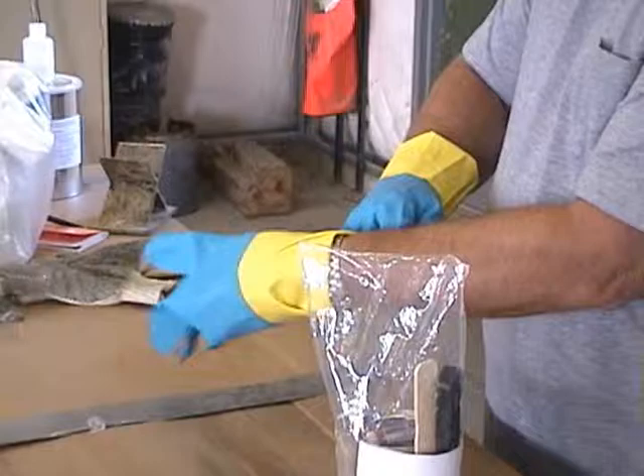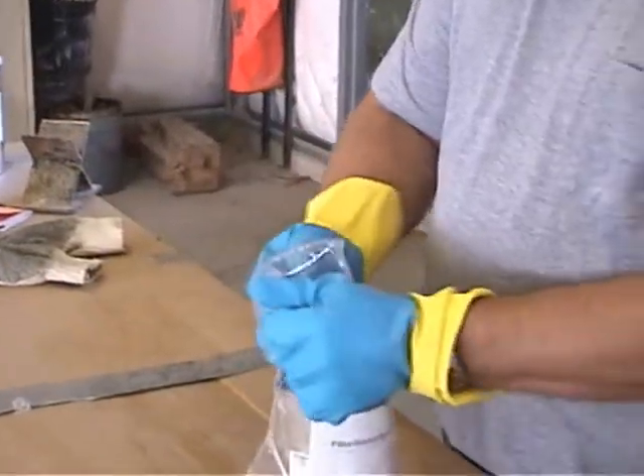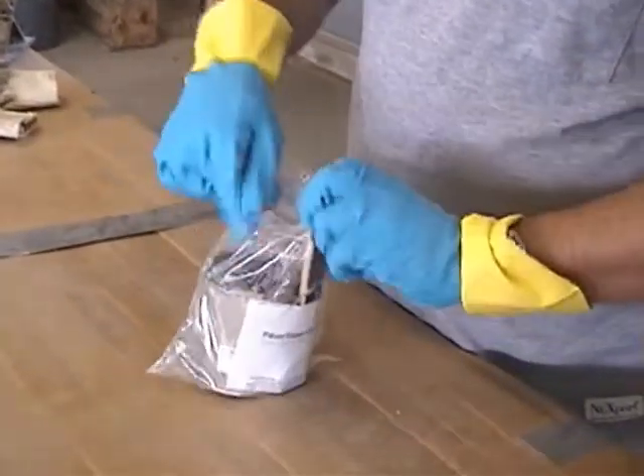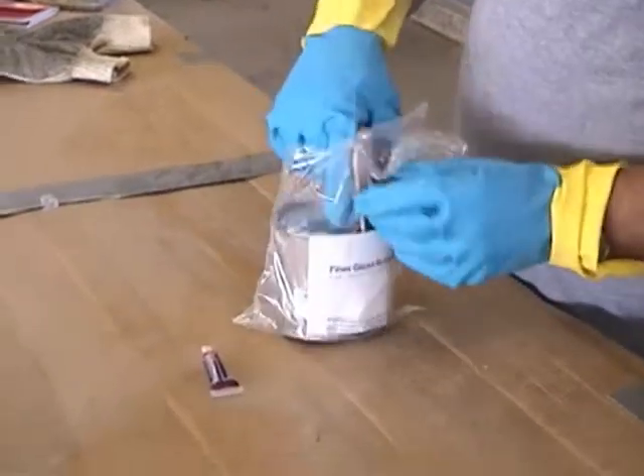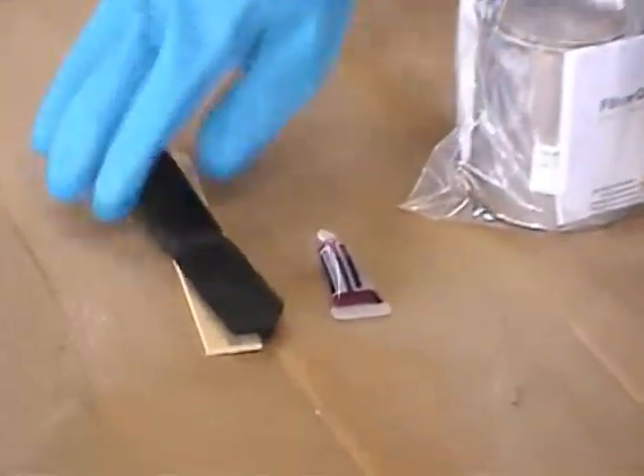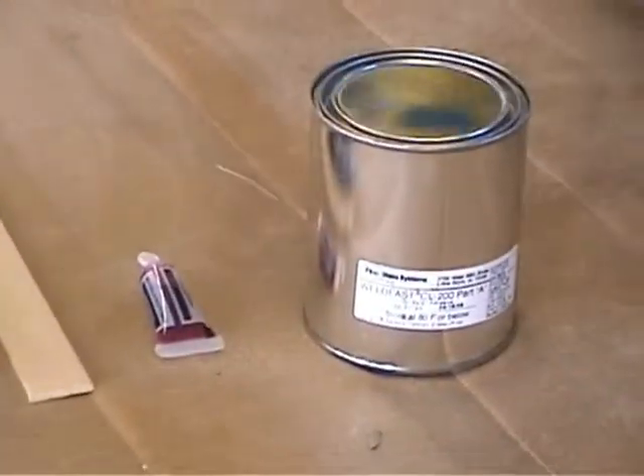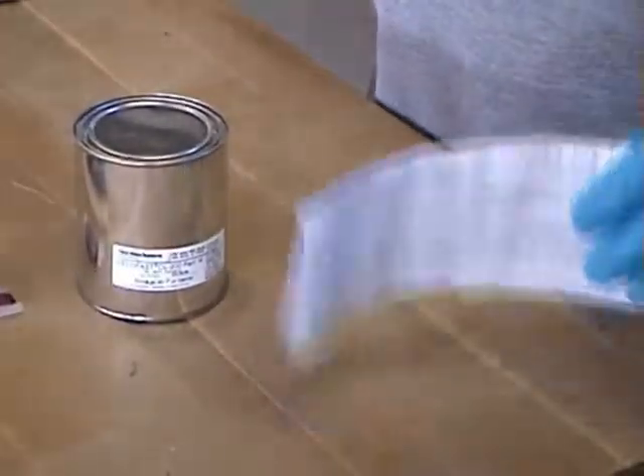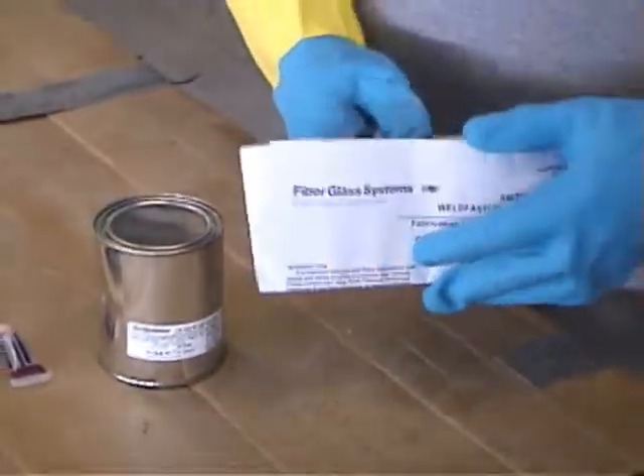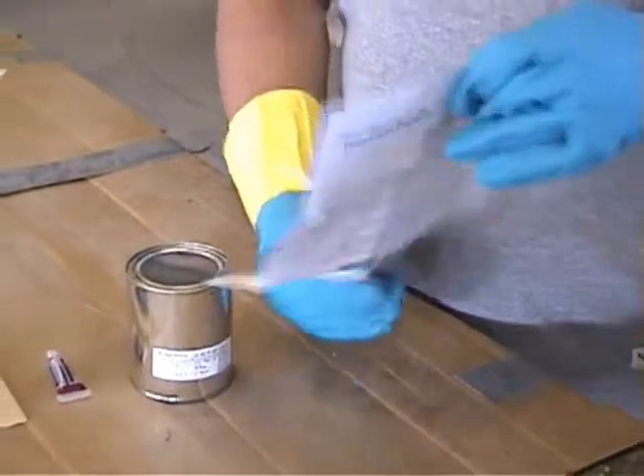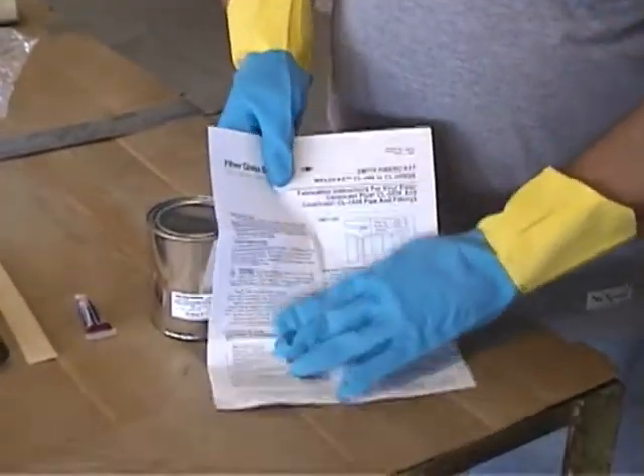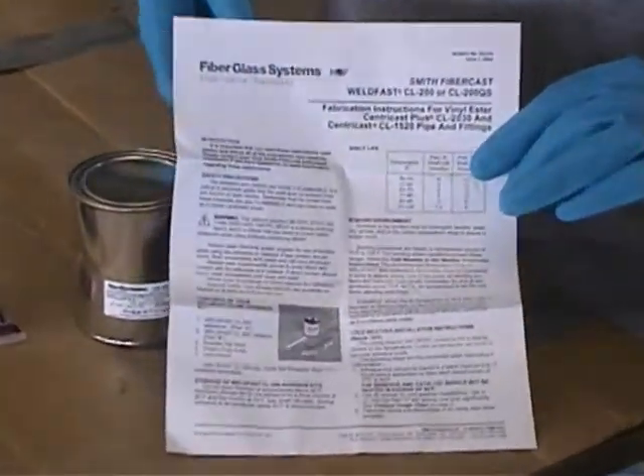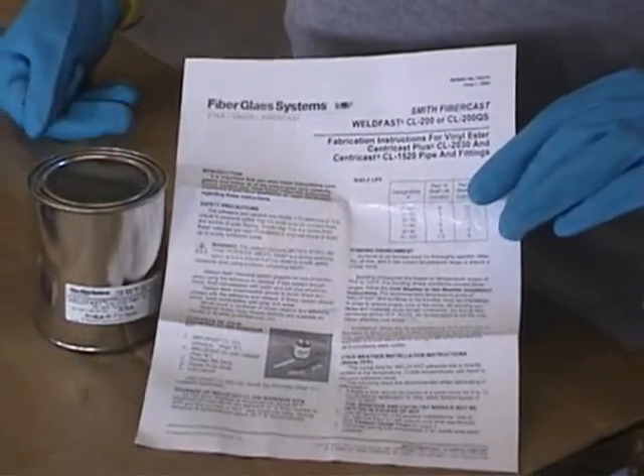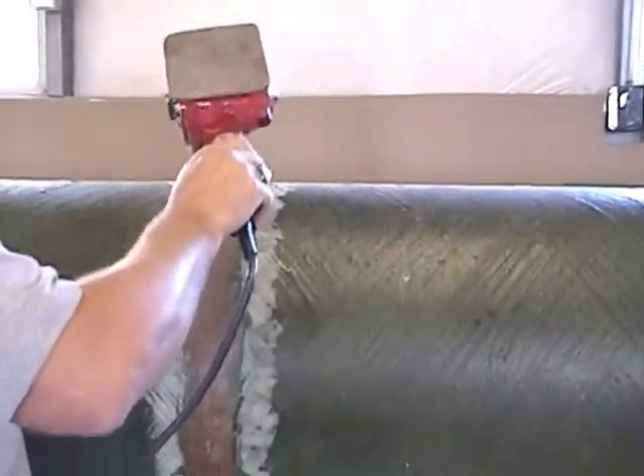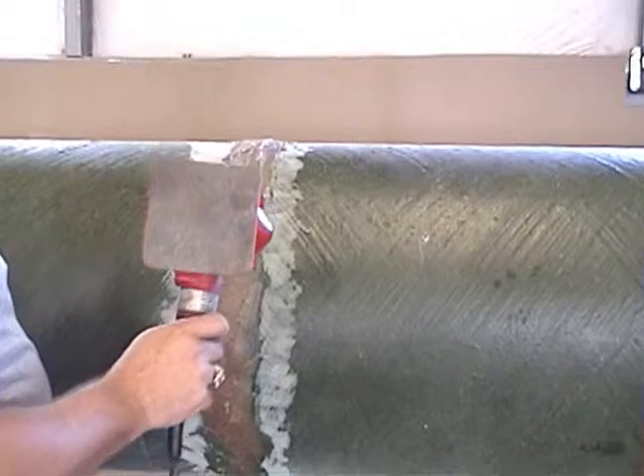The next step is to mix the enclosed adhesive using the elements supplied with the kit, including rubber gloves, catalyst, spatula, mixing stick, and Part A. Refer to the enclosed instruction sheet for specific directions for mixing the catalyst. This material is good from 60 to 100 degrees, which will cure in 24 hours, or you can accelerate the cure with a heat gun in less than 1 hour.